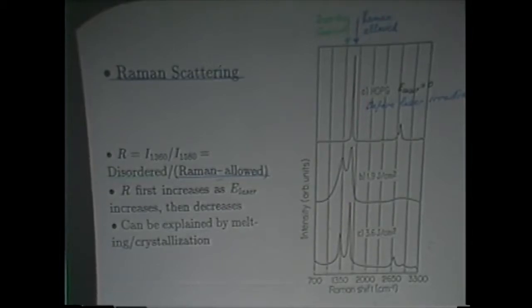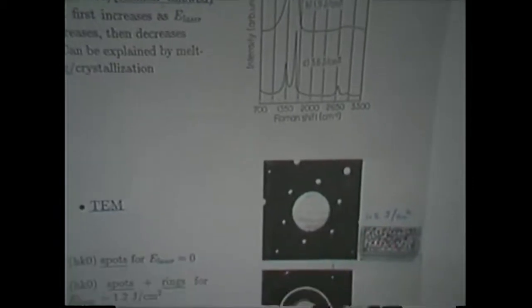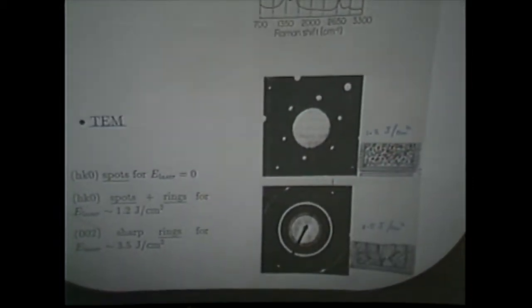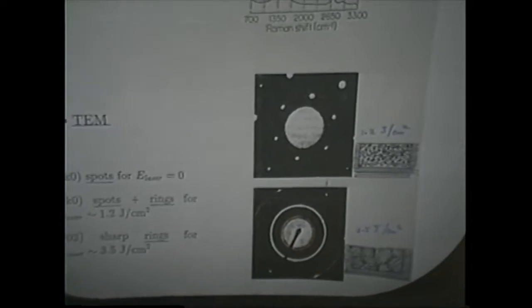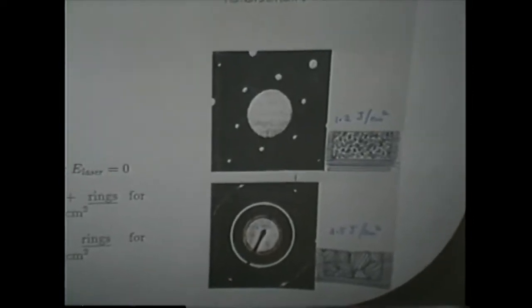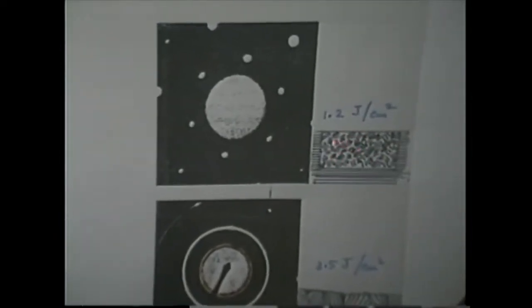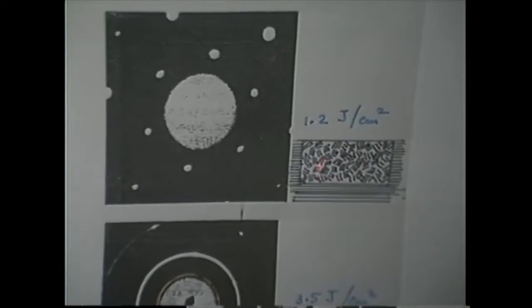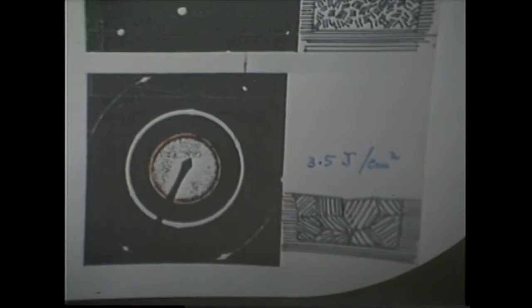Well, that's explained here in this little picture, where initially the material is molten for a very, very small time. The rapid solidification forms very small little crystallites, and the little crystallites are at all random directions, so you get a rather disordered system. But if the molten region is allowed to stay molten for a longer period of time, the little crystallites grow. And in fact, some fraction of these crystallites might be oriented normal to the original crystallites, so we get some interesting results from that.